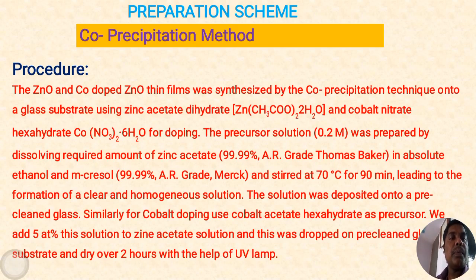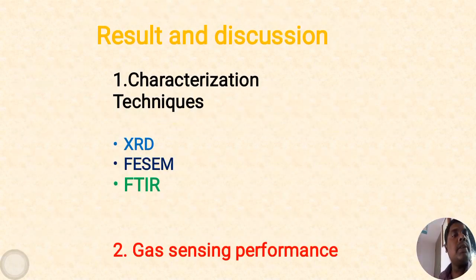Similarly, for cobalt doping, we use cobalt acetate hexahydrate as a precursor. We add 5 atomic percent in solution to the zinc acetate solution, and this was dropped on a pre-cleaned glass surface and dried over 2 hours with the help of a UV lamp. And here is the formation of zinc oxide and cobalt doped zinc oxide nanostructure.